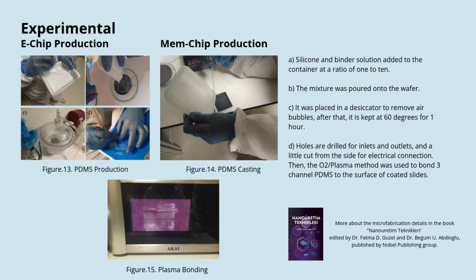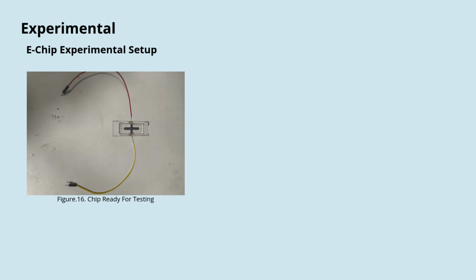After the 1 hour, the chips are cut out from their containers. Holes are drilled for the inlets and outlets via a 1 millimeter punch. The production of the MEM chip is done at this step. For each chip, a little cut from the sides is done for electrical connection, and then the O2 plasma method was used to bond three-channel PDMS to the surface of the coated slides. Wires are connected to the open sides with epoxy and the E-chip is ready for experimentation.